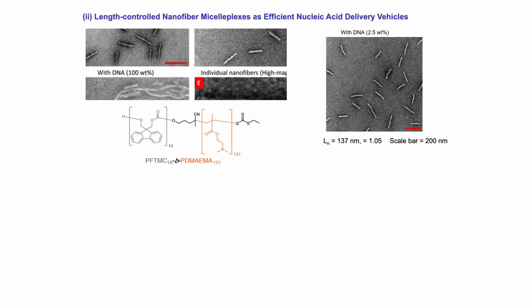The reason we use this is that if you put it in water, it will protonate, and this means it becomes positively charged. DNA, of course, is negatively charged, so DNA sticks to these fiber-like structures, and you can put a lot of DNA into the shell of these structures. And these are actually some of these structures with DNA bound.